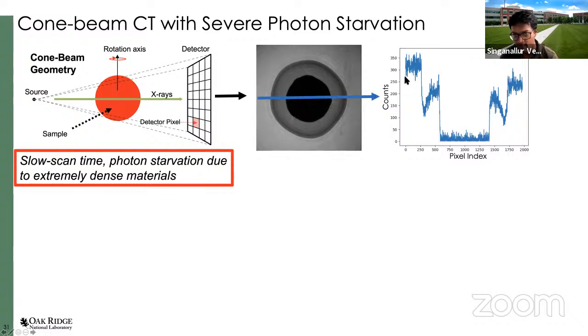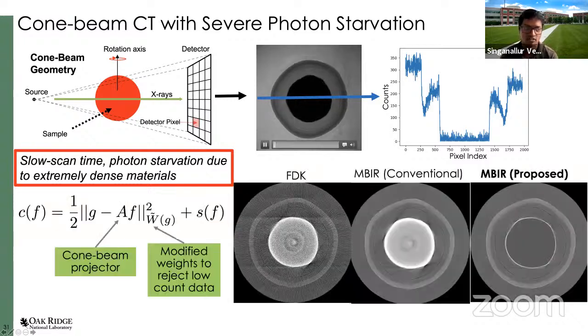So if I plot a line profile, you have high counts as you go here, but as you go towards the core, the counts significantly drop. They're almost zero, not quite there. And this makes reconstructing such data extremely challenging. So we've been developing model-based techniques for this cone beam CT, where we have a cost function based on this. And once again, this weighting term that we have in the cost function can be very important, because it can help us treat this region of the sample very differently.